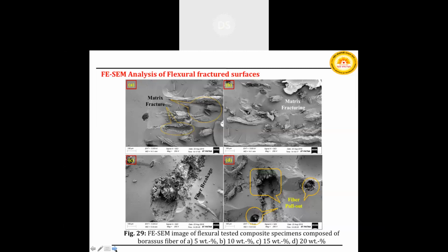During the bending load, the cracks were formed near the void region of the specimen. These cracks started propagating as soon as the applied load started acting on the flexural test specimen, and the failure of the composites occurs.